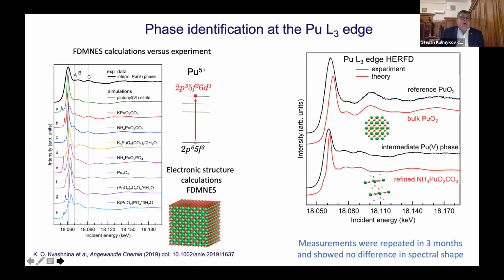Great work was done when we tried to learn what this plutonium-5 phase is. We took different known phases of plutonium-5, which are presented here, and we made calculations versus experiment. The upper spectrum is the experiment, and this is the L3 edge of plutonium, and we analyze these A, B, C regions that are different for these different compounds because they are sensitive towards the structure. You can see that the only plutonium-5 model spectrum that corresponds to our experimental data is a mixed carbonate of plutonium-5 and ammonium.